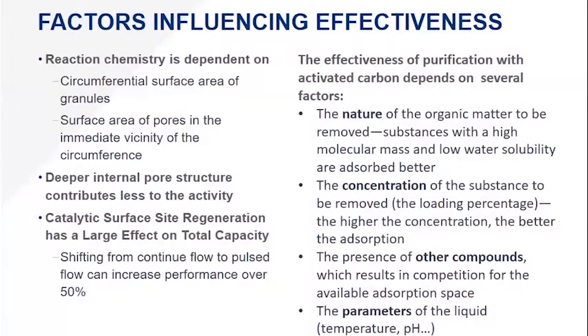When we certify our products at NSF, we do it under continuous flow, not pulse flow. That's critical to understand the difference between our products and other manufacturers. Because activated carbon has this ability when dealing with pulsed flow to reactivate or migrate past contaminants through to other parts of the molecule, refreshing that activation site as it rests. You can get up to 50% more capacity than rated on a cartridge based on pulsed flow. We never state that because we can't predict the pulse flow pattern our customer is going to use, so we test under continuous flow.